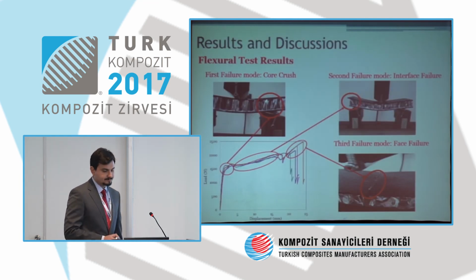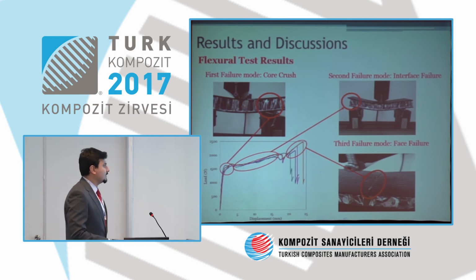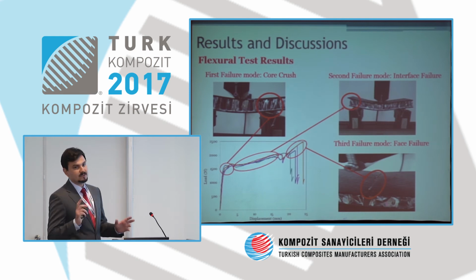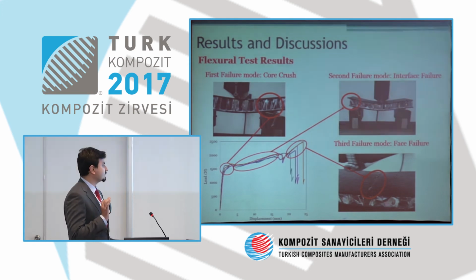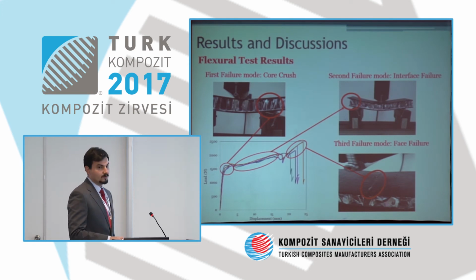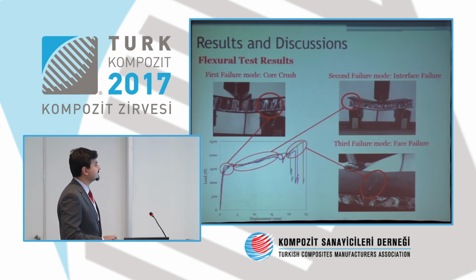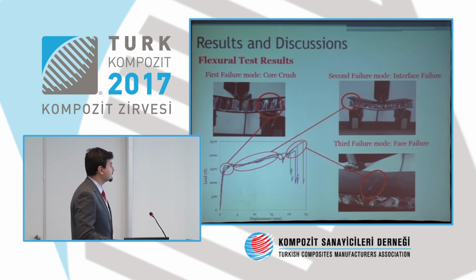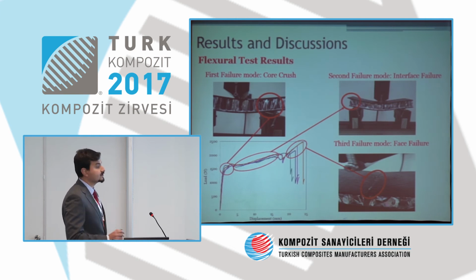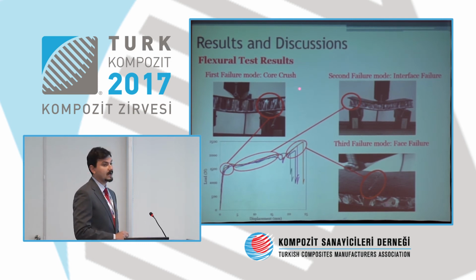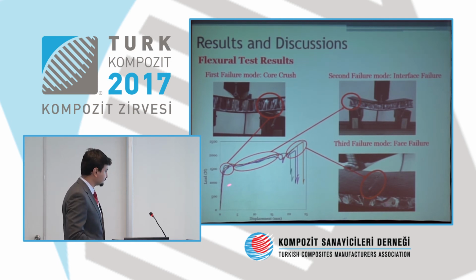And our results. First of all, we obtained the F-ultimate for fatigue test, so that we did the flexural test. This is our load displacement curve for flexural test. We observed also failure modes, and we determined the first failure mode for monotonic load is core crush, as you see here. And it occurs in here.